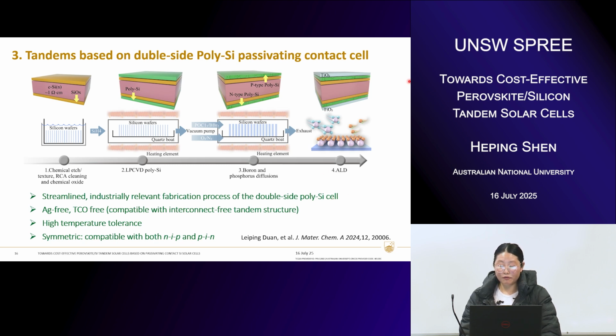The other features of this cell structure, as you can see, are that it doesn't have silver. We use aluminum as the contact, and of course it doesn't have TCO. We don't need any TCO, and I think I don't need to emphasize the advantage of that again. Of course, high temperature tolerance is another factor, and because of its highly symmetric structure, we can use it in both the NIP and the PIN tandem cell structures. That's indeed what we have been doing, and it allowed us to have high performances. But because of the time limit, I will focus on the NIP cell structure in my topic today, because of that innovative interconnect-free tandem structure.